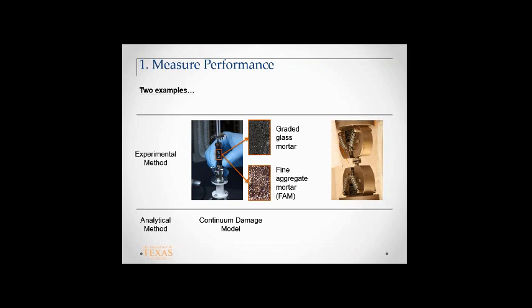Let's say you mix this rejuvenator in a drum, throw in the rest of the stuff, you mix, and it comes out, right? There are two scenarios. One extreme is that because of the high temperatures, transportation and mechanical forces it's being subjected to, everything blends. Although you're not mixing it in a stirrer, the process of carrying it from one place to another, with temperatures at 150, 140 degrees Celsius, very high temperatures that promote diffusion and mixing. So that's one scenario. If that is the scenario, then you are here. The other scenario is that the temperatures and times associated are not sufficient for full mixing.